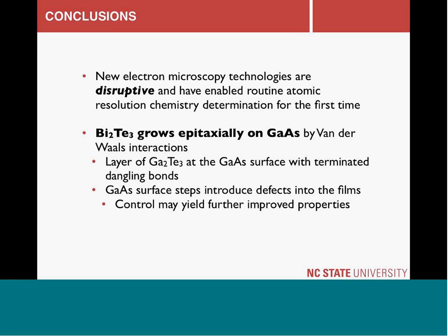And what we do with this is, I mean, this telluride grown on these films has been around for 10, 15, 20 years now. And to actually understand that interface has only been made possible through these technologies. And for telluride, we saw why it grows epitaxially on gallium arsenide in the first place. It's that we're running a third phase through that boundary that allows us to separate the two. By being able to directly study defects, we can begin to understand how to improve materials, even further at the atomic scale.